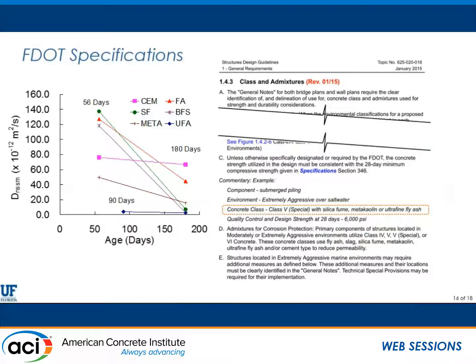As part of this work, there was some prior research where we did bulk diffusion tests with these ternary blends and looked at diffusion coefficients and the improvement in the concretes. The DOT has since, a few years ago, added this to their construction specifications: silica fume, metakaolin, or ultrafine fly ash, along with the addition of fly ash as well for their piles.